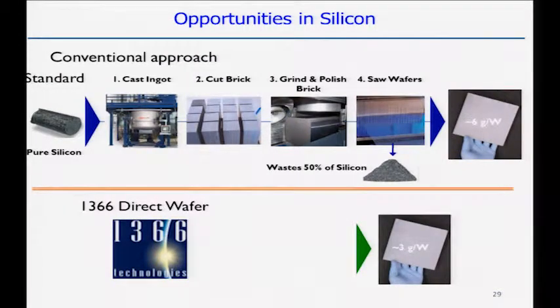And so right now in a silicon module that you buy anywhere around the world, half the cost is the polysilicon. Before you've doped it, before you've done any of the lithography for the electrodes or anything, it's just the polysilicon. Right now what you do is you saw it up and you cut it into wafers about 150 microns thick, but you can't get much finer than that. You don't need that. Even though it's an indirect band gap material, you can have light trapping techniques, you can get away with 30 microns, maybe even less.